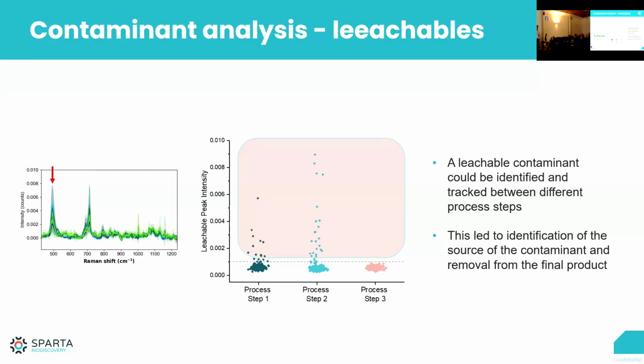Critically, we could identify what the contaminant was and that it was associated with the particles, because we can really see it on the particle that we trapped. We saw the normal signal plus the contaminant signal, which again informs you what kind of purification method you might need to use, versus a solution-based contaminant.